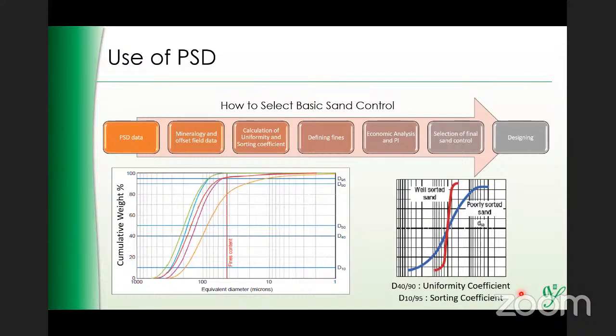The uniformity coefficient tells you how uniform your sand particles are. So the more uniform your sand particles are, the easier it is for you to design a filter through which your sand cannot pass. And sorting coefficient is the difference in size between the smallest particle to the largest particle. So the sorting coefficient is also similar to uniformity, only it gives you the range of your particle sizes. If the range is very high, once again, it's very difficult for you to design a sand control for the huge range. So these are the two parameters we look at.